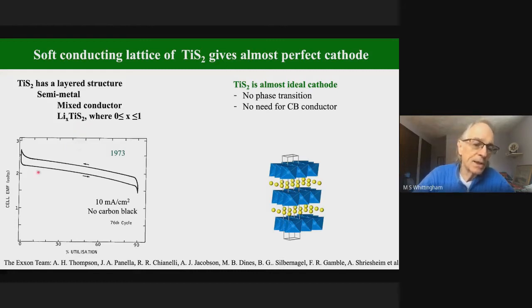And you can see this in this voltage plot. This is the cell voltage. You could put free energy here. It's the same thing. You see the voltage slowly decays in a continuous manner, showing this is single phase. Then when we reverse the current, we recharge it, it follows exactly the same curve. This curve drops because as we put the electrons into this titanium disulfide, we're filling up the conduction band, so we get less and less energy as we put more and more electrons in. I should point out this was run at 10 milliamps per square centimeter, probably higher than any lithium battery today.